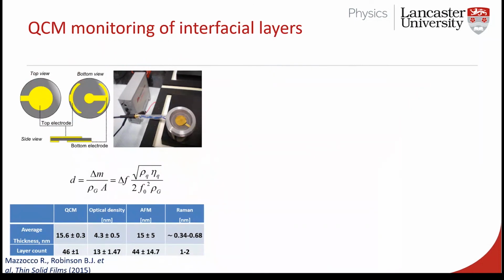Another capability I briefly want to talk about is a way we can go about measuring the interactions of these surfaces and films with the outside world. This is a technique we have and we use extensively called quartz crystal microbalance. This is an ultra precise mass sensitive technique. So we take a quartz crystal, in this case you can see it here in this device. It has electrodes on either side, and where those electrodes overlap, if we apply an alternating electronic field across those electrodes, the whole crystal vibrates. And if we measure that vibration, we can tell what's going on in terms of the mass on the surface and also the mechanics of that mass.